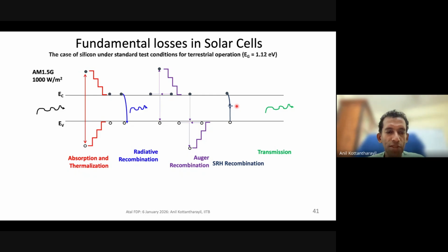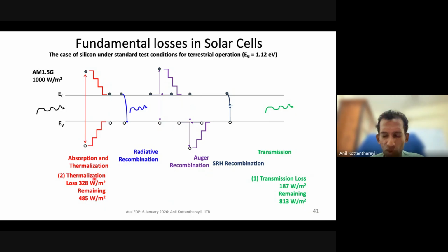Now let's quantify this. The case of silicon is Eg equal to 1.12 eV, and you can calculate the transmission losses as about 187 watt per meter square out of 1000 watt per meter square. This is easy to calculate if you know the spectrum. Thermalization losses are about 328 watt per meter square. So you can see only about 485, less than half, remains after transmission and thermalization. These are fundamental losses. You can't do anything about them. Radiative recombination losses: about 162 watt per meter square is lost.